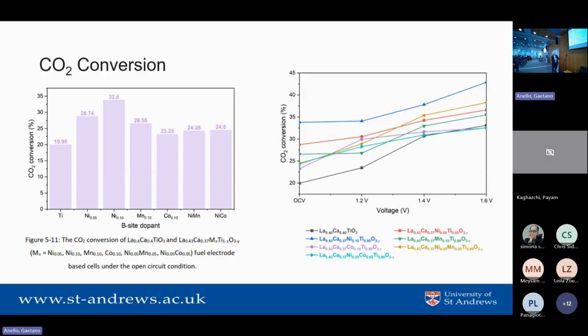So with the nickel, it's better and better. With cobalt, it's not quite so good. But actually, if you look at the black, the bottom, that's got no nickel nor cobalt. So no reducible transition metal, only titanium. And if you reduce titanium hard enough, you get enough oxygen vacancies that the perovskite works without the exsolution. So the substrate is clearly becoming more active.